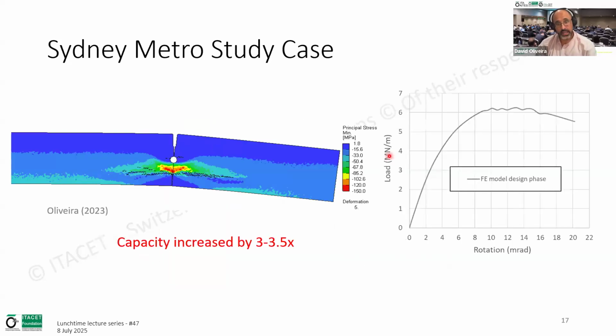And we started simulating our joint rotation numerically as well. What we observed is that by doing nonlinear stress modeling with proper fracture mechanics, we were predicting much higher capacity than those empirical applications by Schnütgen, and also, of course, than what we were originally limited to in terms of linear strength analysis. So we were achieving unfactored values here in the order of 6,000 kilonewtons per meter, 6 meganewtons.